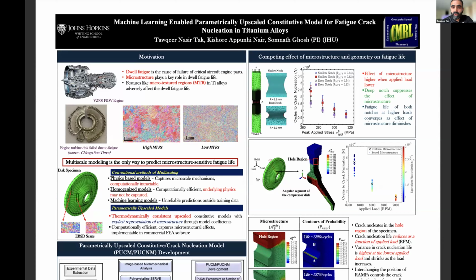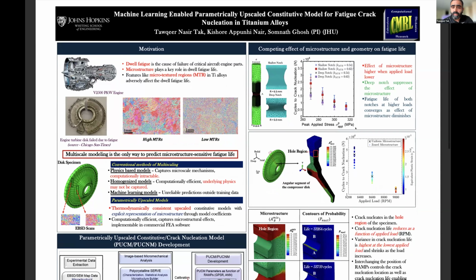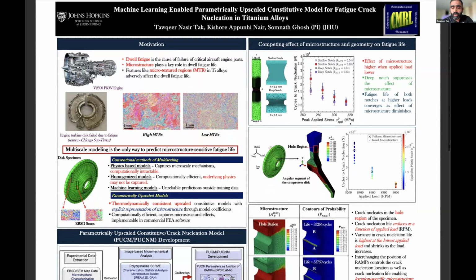We can see that the shallow notch has higher crack nucleation life. Also, we can see when the MTR intensity is higher, the crack nucleation life comes down. Whereas this variance shrinks as the load increases. So that means as the load increases, the microstructure effects go away.